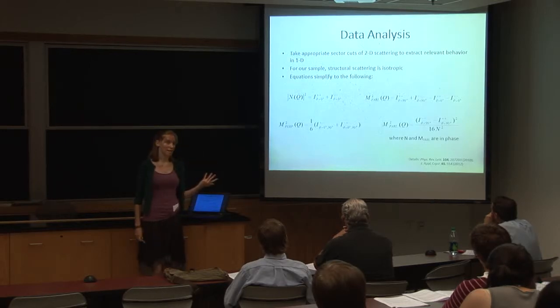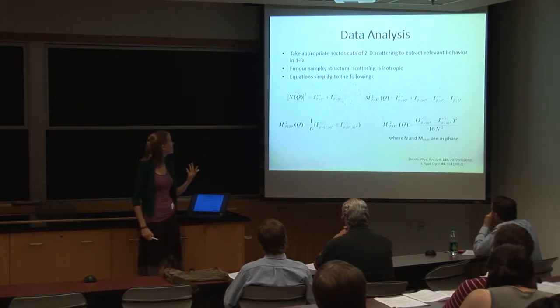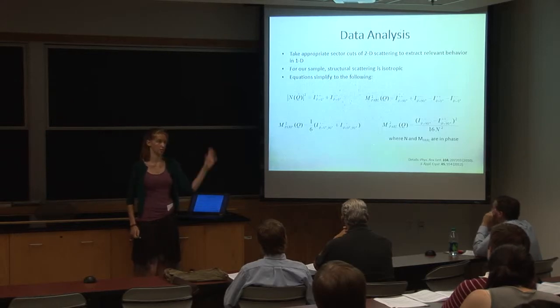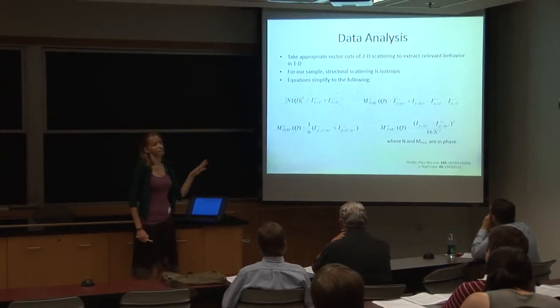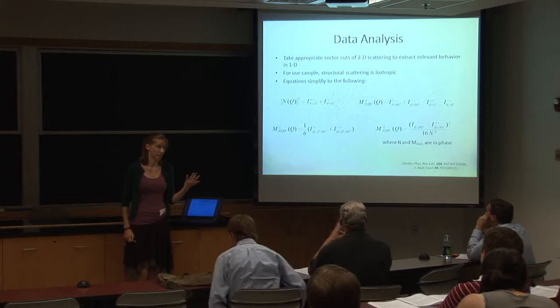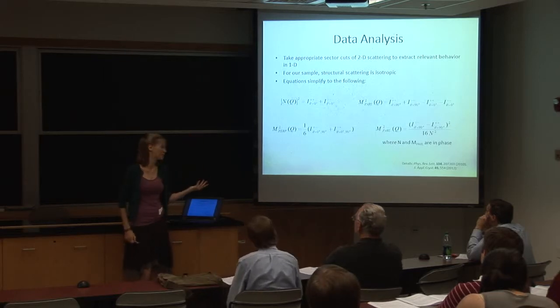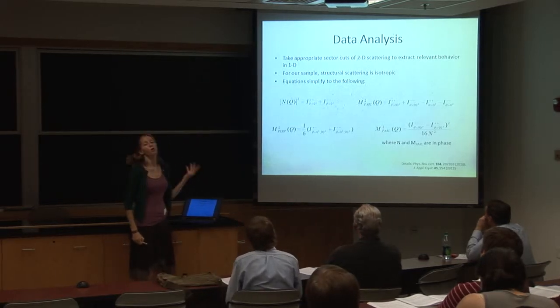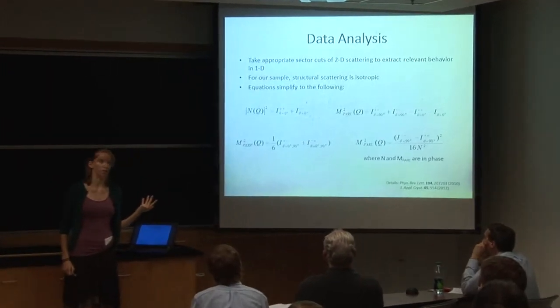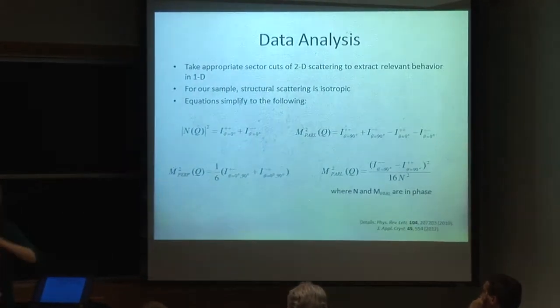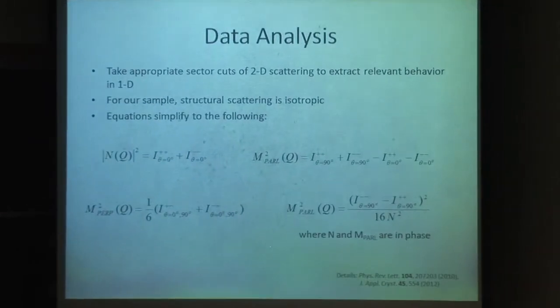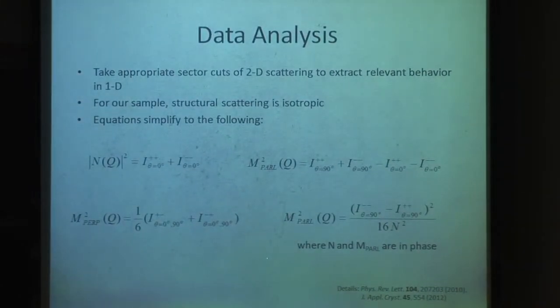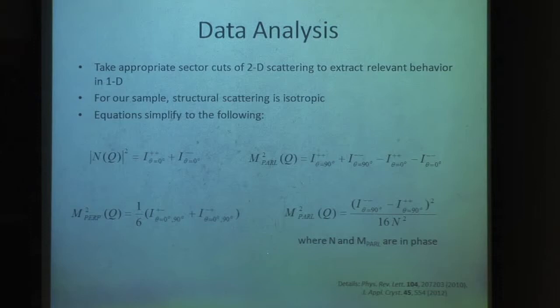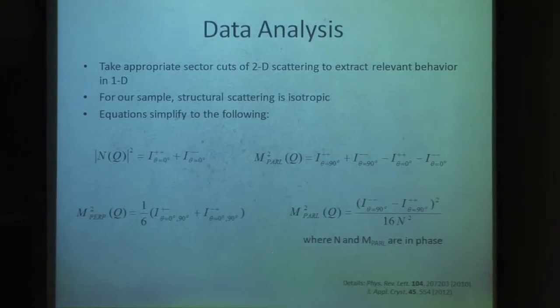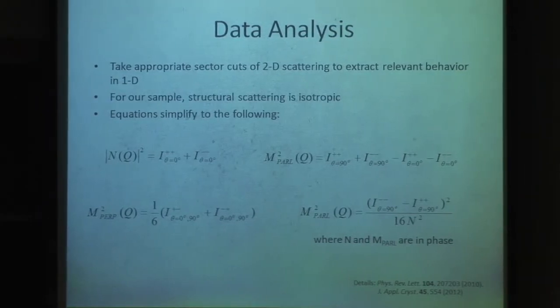So when we analyzed our data, we were taking sector cuts of our 2D data, that big, nice circle, and extracting relevant behavior to get 1D data, nice, normal graphs like you would expect. For our sample, we had isotropic structural scattering, which means it didn't matter what angle we took our cuts at for our structural scattering. Our crystal was the same no matter what, in structural world. In magnetic world, it did matter. But because of that structural scattering and our geometry, our equation simplified to the following.